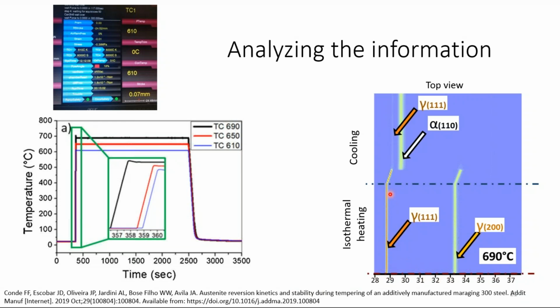all the 30 minutes. When you start the cooling, you are going to see that this austenite changes, the intensity is lower, and then it's just a shadow. It remains very little austenite. But when you transform this austenite, it becomes martensite, and then the peak of martensite is very intense. This is a top view. You have a range of diffractograms from here to the top, and it's basically another way to see the evolution.